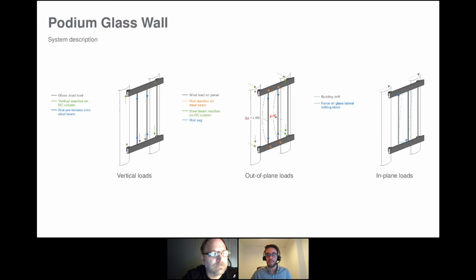For in-plane load, since Hong Kong is not a seismic zone, we didn't have a problem of seismic load, but we did clearly have the drift of the structure. So the system can kind of rock, because the lateral stiffness of the rod is basically very, very minimal, and therefore they can be assumed to rotate and drag the panel together with them when the building moves. It's also fair to say that the lateral drift of the building was quite minimal. I think we were talking about around 20 millimeters. Considering the 15 meter tall height of the system, that is basically a criterion of roughly 1 over 800. So quite minimal movement to be absorbed.